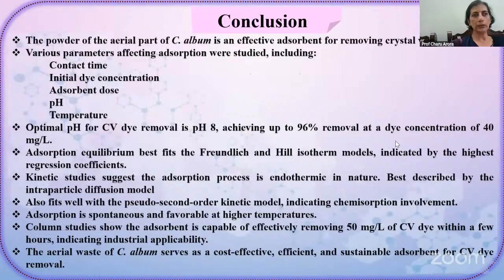These are the conclusions. It is a very efficient material. We have studied the effect of contact time, dye concentration, dose, pH, and temperature. The optimal pH was 8, with up to 96% removal at 40 ppm concentration. Adsorption equilibrium was best fit using the Freundlich and Hill isotherm models. The kinetic study suggests that the process is endothermic in nature, and it is best described by intraparticle diffusion.